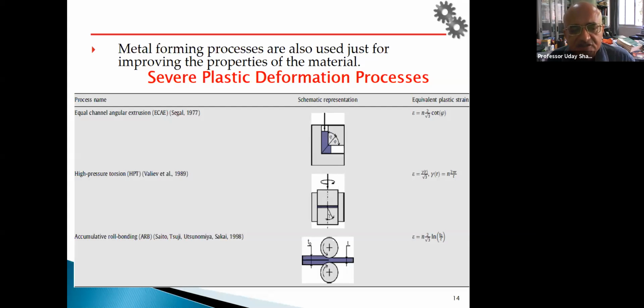And similarly, another one is related to rolling. This is called accumulative roll bonding. In this, if I take some thickness, let us say 10 mm, and pass it through the rolls, the thickness becomes 5 mm and the length becomes double if it is plane strain rolling. And then I cut it into 2 pieces, and again put one above the other on the input side. So the thickness again becomes the original, and again I pass it through the rolls. Then these sheets will get bonded, and again there will be reduction. This process I can repeat several times.